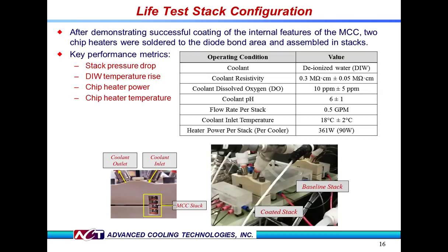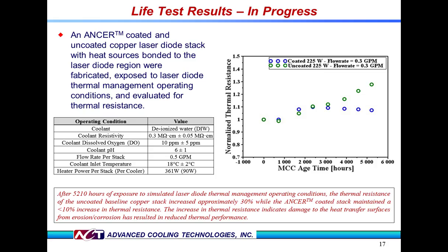In the pictures on the lower right, you can see where the MCC stack is located within the test setup. The picture on the right shows the location of both the baseline copper MCC stack and the ANCER-coated stack. Test setup parameters and values, including coolant pH and heater power, are listed on the top right. The key metrics that are monitored include pressure drop, deionized water temperature rise, and chip heater power and temperature. Now that you have an idea of the test setup, let's look at some more recent, longer-term results.